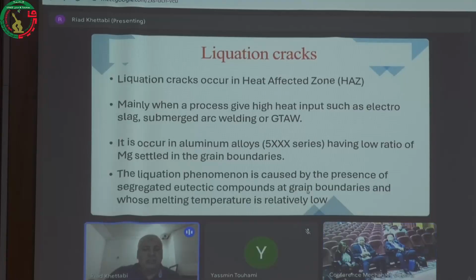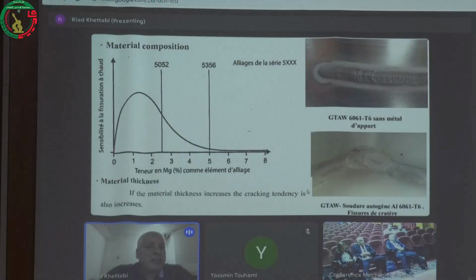So the liquation phenomenon is caused by the presence of segregated eutectic compounds at the grain boundaries, whose melting temperature is relatively low compared to the grain melting temperature. So we present here the example of the 5000 series. We have here gas tungsten arc welding of 6061 T6 without filler metal. And here, the gas tungsten arc welding with autogenous welding of the same aluminum alloy 6061 T6.